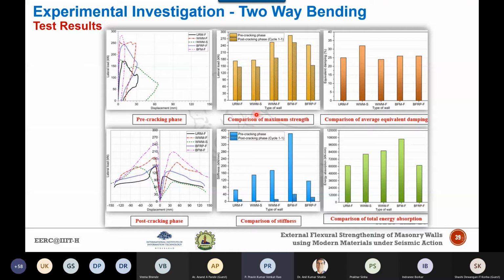Amongst all the retrofitted walls, if you see, the basalt fiber mesh wall has shown the highest increase in strength and also the highest increase in stiffness, because the entire wall has been covered with the reinforcement, whereas in other cases only strips of finite width of reinforcement have been provided.